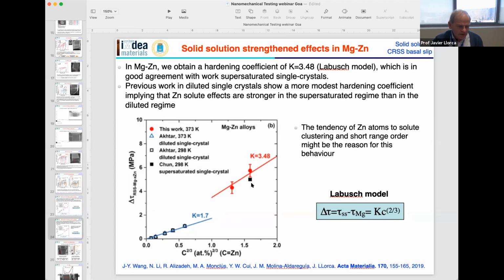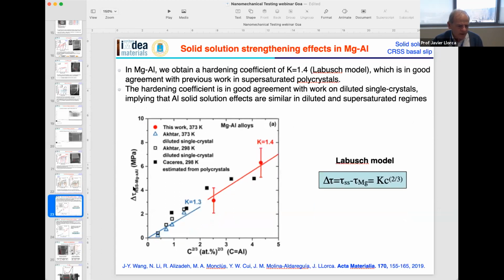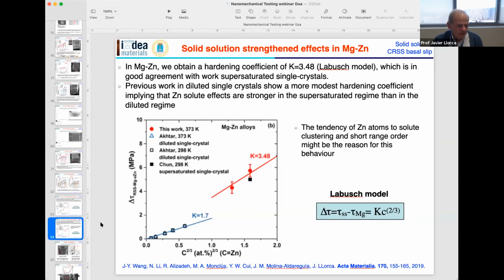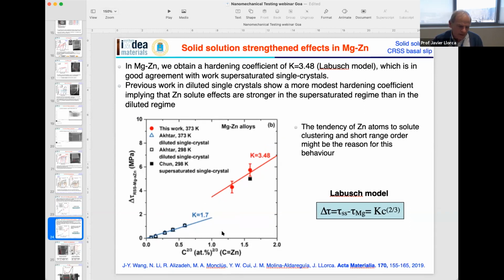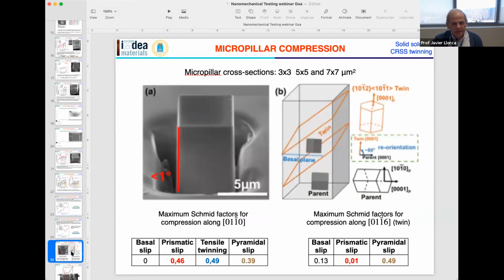In any case, one thing that is important: you can see the solid solution strengthening effect in magnesium alloys, for basal slip, both for zinc and in the previous case for aluminum, is very small. You only increase the critical resolved shear stress by 4, 5, 6 megapascals in the case of aluminum, and by a similar amount in the case of zinc. So it means that basal slip continues to be the softest slip system, and the main objective, to increase the critical resolved shear stress for basal slip to decrease the plastic anisotropy, was not achieved in this particular case.